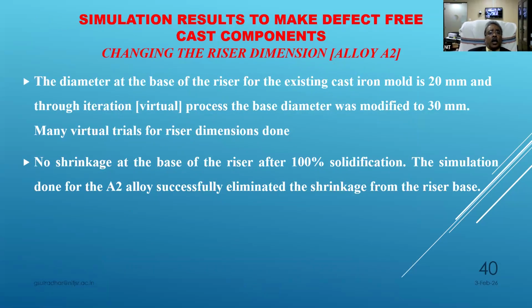Now the simulation: what we want ultimately is a defect-free casting, so we change the riser dimensions. My student, Dr. Tripathi, found that the diameter at the base of the riser for the existing cast iron mold is 20 millimeter. In the laboratory it is difficult and time-consuming, but in simulation, you can do n number of iterations, and in those iterations the base diameter was modified to 30 millimeter.